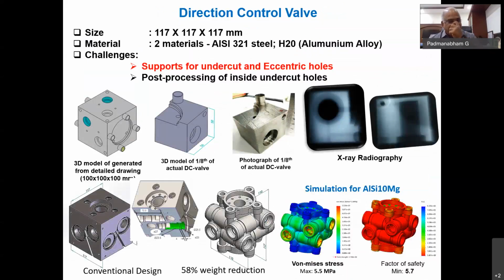And the direction control valve, the video which you have seen, starting from a solid block on the left side to the actual design which is showing in the red color or the middle one. What we did is first started with a skeleton of the flow patterns that are required and started adding material virtually through the CAE, and then depending on the stresses that are expected and adding a factor of safety, added the material knowing the properties and arrived at this design. So finally, with a factor of safety of 5.7, thinking that we should be able to withstand 5.5 megapascals von Mises stress, we are able to achieve a design with 58% weight reduction.